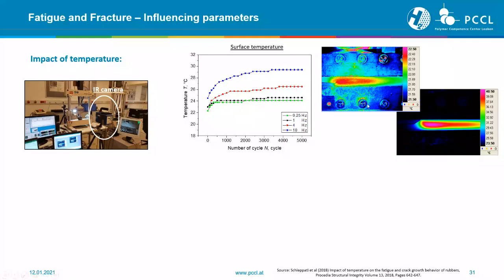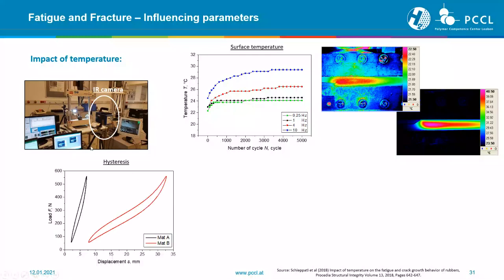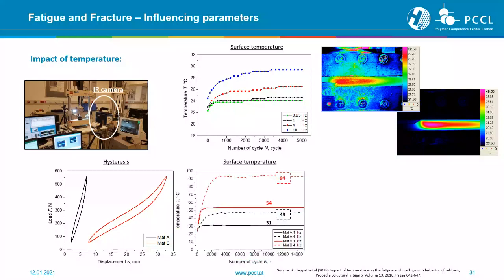Additionally, not only the specimen geometry has a big impact, also the material performance has a big impact, which means that for material A, for example, we have a more or less linear behavior when we're talking about elastomers, whereas material B has a strong non-linear material behavior with high deformations, which ends up in much higher temperatures. When we think of 1 and 4 Hertz of Dumbo specimens in this case, in the comparison from 1 to 4 Hertz we're ending up nearly at 100 degrees, which is a huge impact of temperature on our material when we think of the impact that we've seen before on thermo-oxidative aging for HNBR.